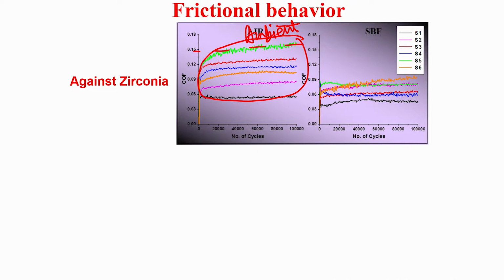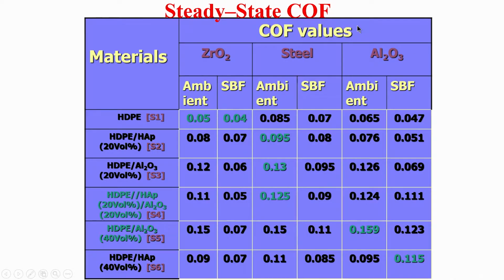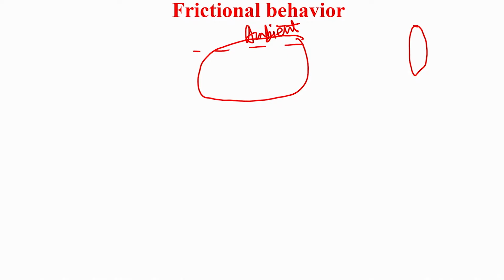These are the different grades of materials: high density polyethylene. S1 stands for pure high density polyethylene, or unreinforced. High density polyethylene with 20 volume percent HAP is S2. High density polyethylene with 20% alumina is S3. High density polyethylene with 20% HAP and 20% alumina is S4. High density polyethylene with 40% alumina is S5, and high density polyethylene with 40% HAP is S6.